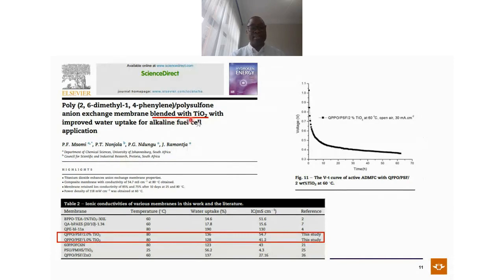So we looked at blending titanium dioxide with the same polymer. And if you can see the performances that we got, this table shows a comparison of the membrane that we made compared to membranes found in the literature. As you can see, at 80 degrees, we are able to get an ion conductivity of about 54 and 41. When you compare with other materials in the literature, you can see that our membrane had one of the highest ion conductivities of its time. This was also a 2018 paper. So we were successful in showing that metal oxides are able to improve the membrane in terms of its conductivity.